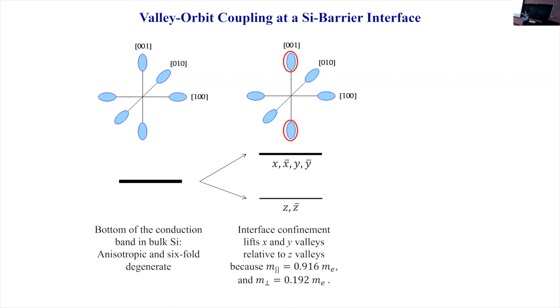Okay, so let's say the growth direction is 0, 0, 1. Then because of the mass anisotropy, the dispersion near these conduction band minima is different along one direction relative to the other two directions. The effective masses are different, right? One is 0.9, the other one is roughly 0.2. And because of that mass anisotropy, four of the bands will go up relative to two of them.